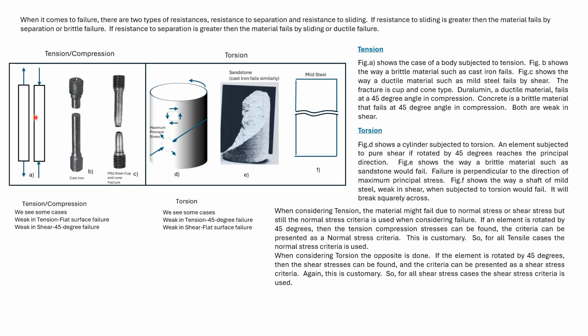Also under tension, a mild steel rod fails by cup and cone fracture. This failure is related to shear. Under compression, duralumin fails at 45 degrees to the horizontal. Similarly, concrete fails at 45 degrees to the horizontal.